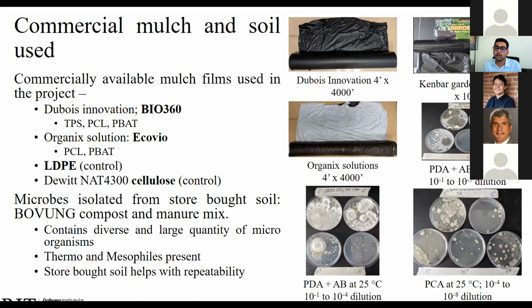This shows a potato dextrose agar plate with antibiotics, which restricts the growth of bacteria. So these are all fungi colonies, and you can see many different types of fungi growing at 25 Celsius. And these are 10 to the -4 dilutions. This also shows that there are huge quantities of microbes. Same thing for the bacterial colonies. We were able to isolate from 10 to the -4 to 10 to the -8 dilution. And you can see different types of bacterial cultures and colonies.